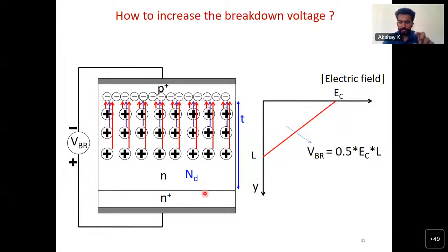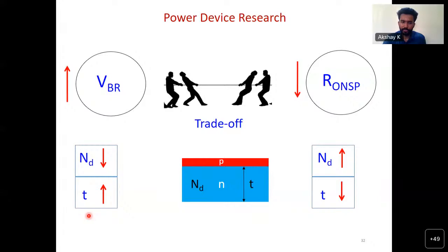And also you need to have a sufficiently thick layer so as to support that voltage. So decreasing doping and increasing thickness will give you high breakdown voltage. That's the summary. But on the other hand, this will lead to high on resistance, right? Because the lower the doping, the higher the resistance. And if you increase the thickness also, you know that resistance is proportional to the thickness, right? And then that also leads to high resistance.